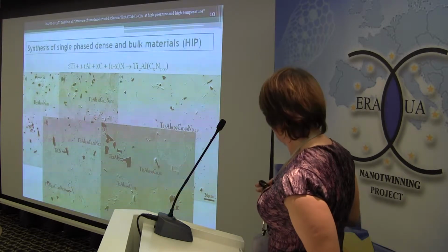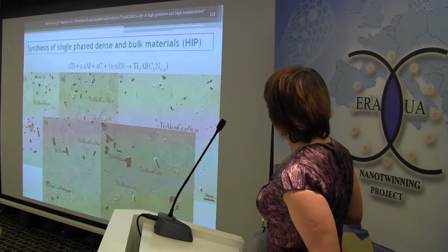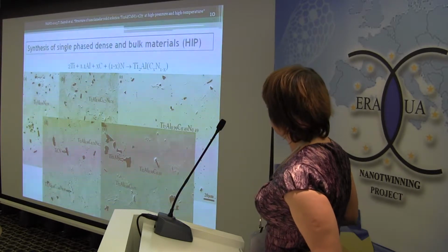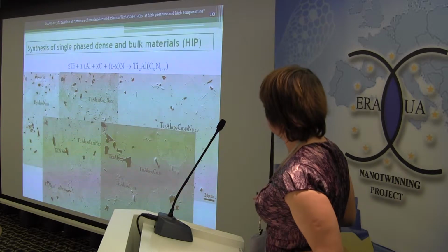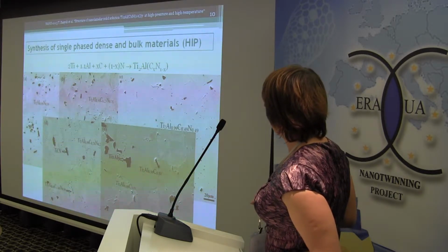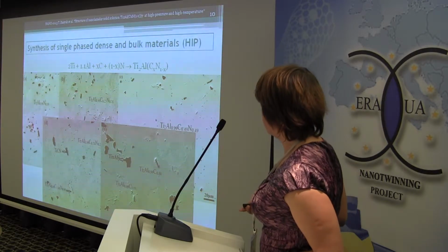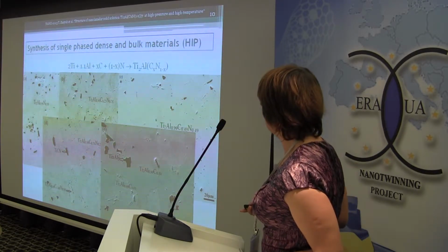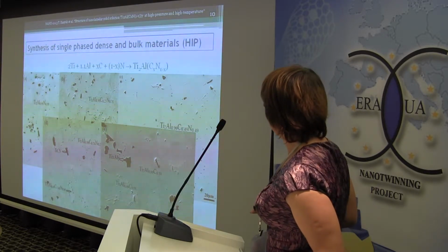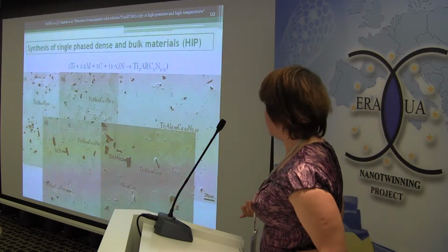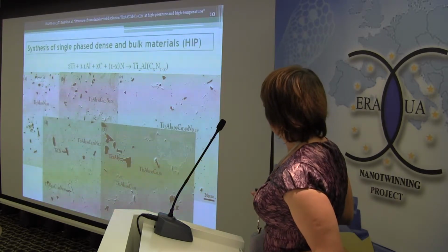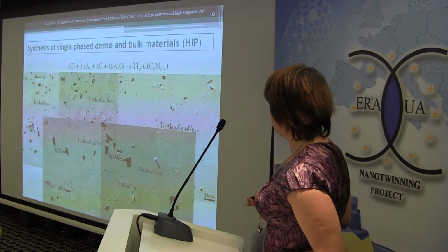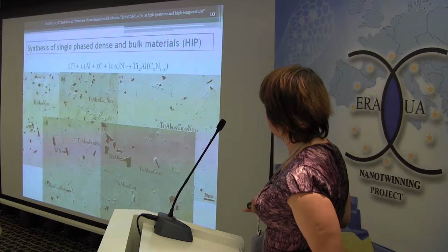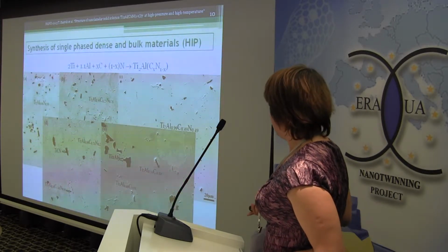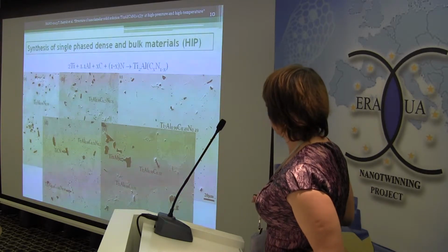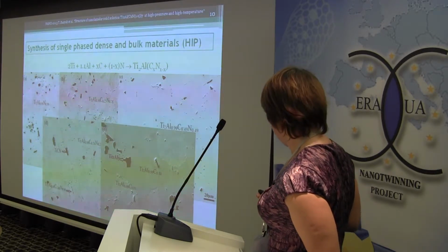Also, before the synthesis we added an excess of 10% of aluminium to the initial powder, because we lose this element during the synthesis process by evaporation. Using EDX analysis, we estimated that in our solid solution the average ratio between titanium and aluminum is equal to 2. That confirms this loss of aluminium.